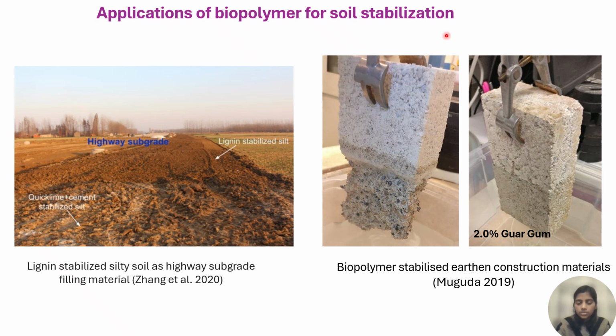A simple dip test was performed, soaking the blocks in water for about 10 minutes, and the results are striking actually. The untreated block lost about 15% of its mass, while the biopolymer-stabilized blocks lost less than 5%. So this shows how even a small amount of biopolymer can significantly improve the water resistance and durability, making soils much more suitable for construction applications. It's a simple but effective way to enhance traditional earth materials sustainably.